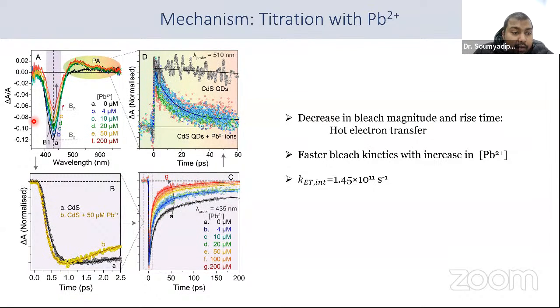Now, this is the kinetics part. You can see the bleach signal kinetics also getting faster. For the photoinduced absorption, it can be easily seen that with increase in lead 2+ concentration, the photoinduced absorption signal also increases. Why is that? This is basically due to the Stark effect.